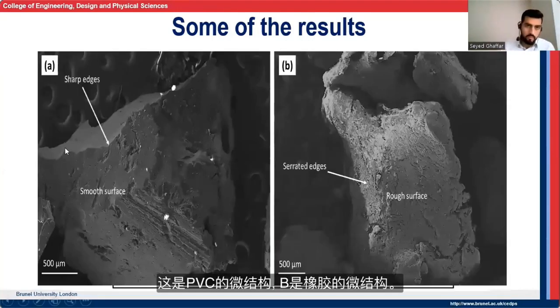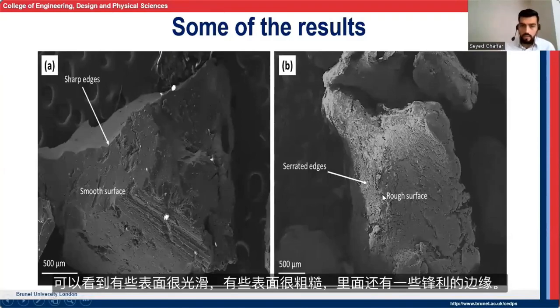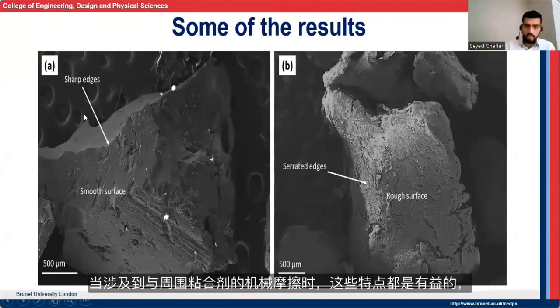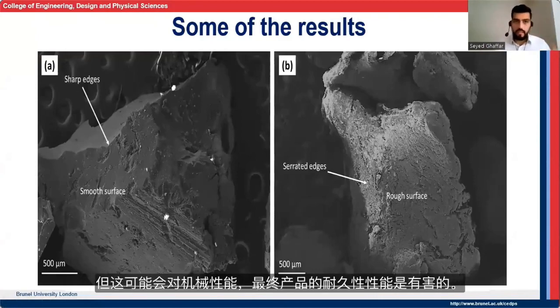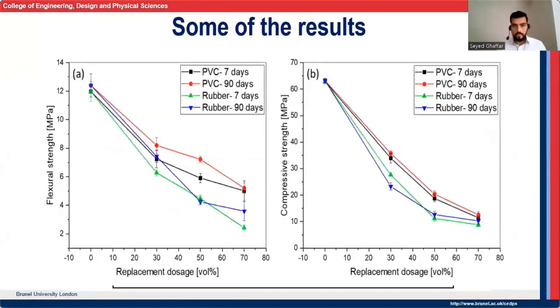So this is the microstructure of the PVC, and B is the microstructure of rubber. You can see that there are some smooth surfaces, and some of them have very rough surfaces. There are some sharp edges inside them, and all of these could be beneficial when it comes to mechanical entanglement with the surrounding binder. And that could be really detrimental for the mechanical properties, for the durability properties of the end product, the resultant concrete.